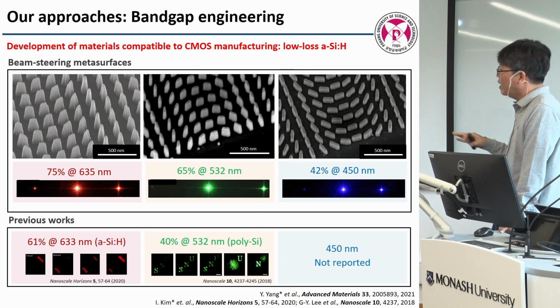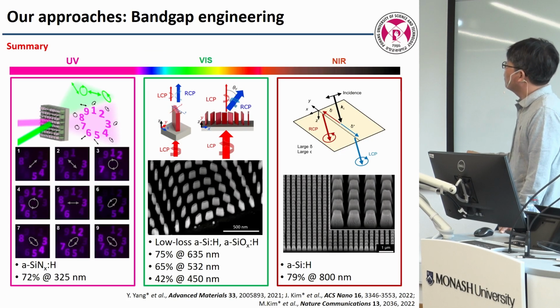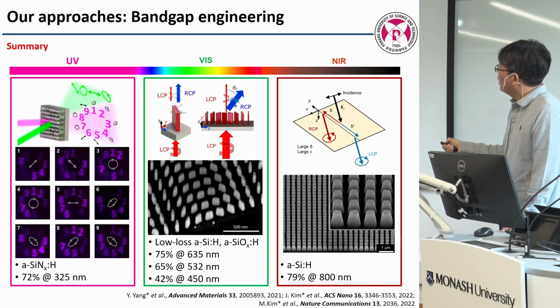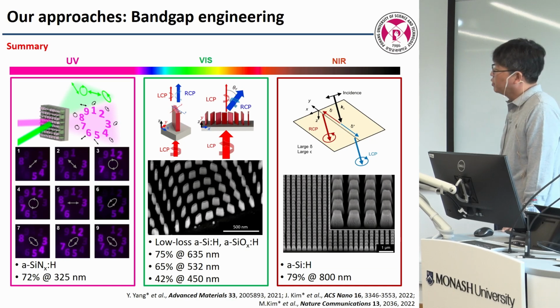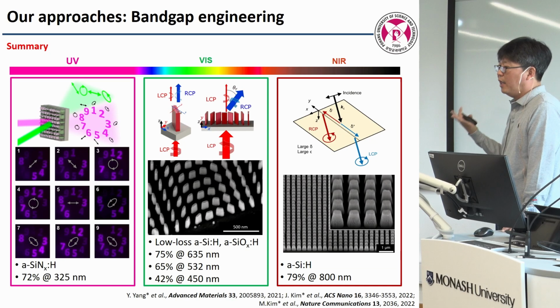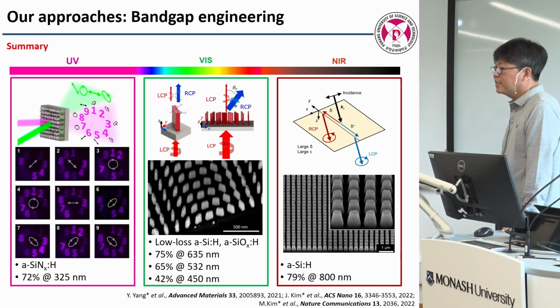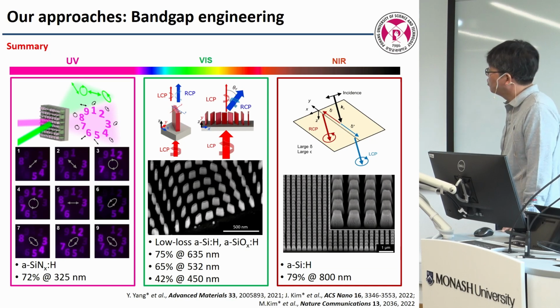And this is some baseline, and CVD is cheaper. This is further expanded to IR. Obviously, silicon is good in IR. And further to UV, with nitrogen doping, whereas the visible uses hydrogen doping. So this is one CVD material, and then deposit, exposure, and etching. This is a typical process that you do.